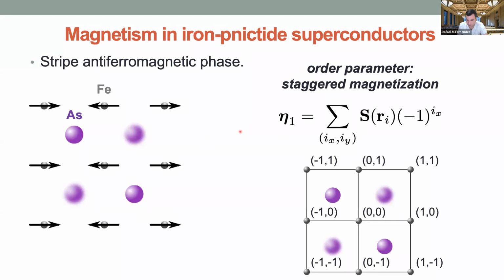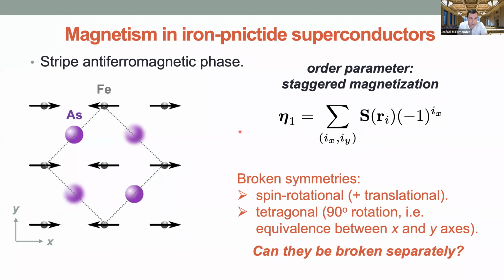That's my order parameter. Now, this ordered phase breaks 2 symmetries. One is spin rotational or translational symmetry, and the other is the tetragonal symmetry. This no longer has the symmetries of a square. As you can see, these two atoms here have spins that are parallel, but these two here are anti-parallel. So this breaks the equivalence between X and Y.